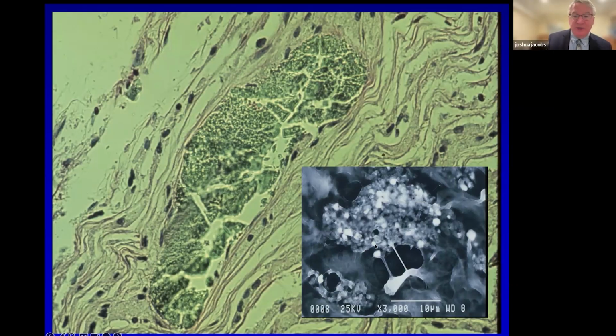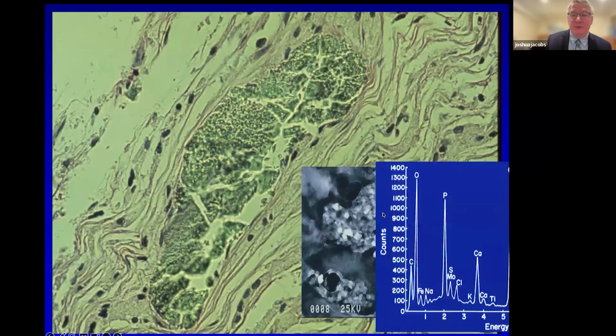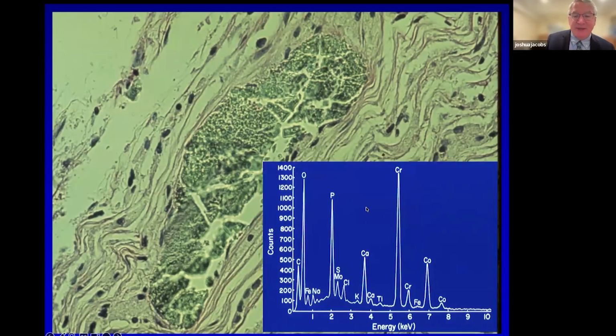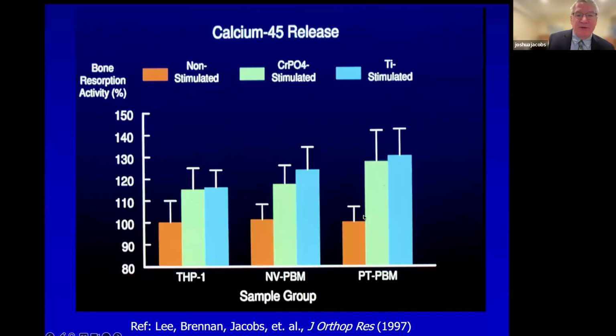Here's an individual histiocyte or macrophage showing the submicron debris that we showed with spectroscopic techniques to be a chromium orthophosphate. We've actually looked at these particles in cell culture. This is an in vitro model of periprosthetic osteolysis where we use rat skulls and we sprinkle particles on top of them. And using calcium-45 release, we determine the amount of bone loss.